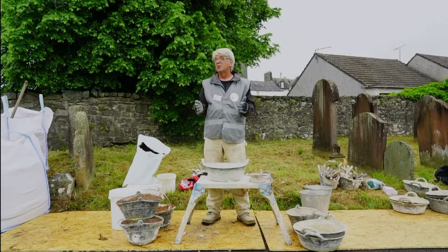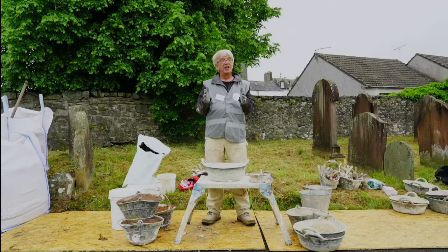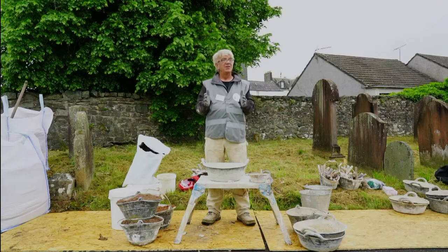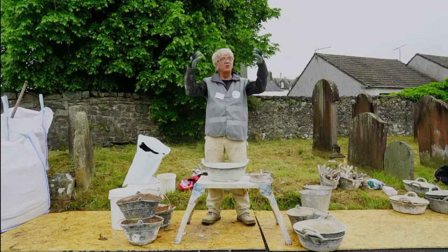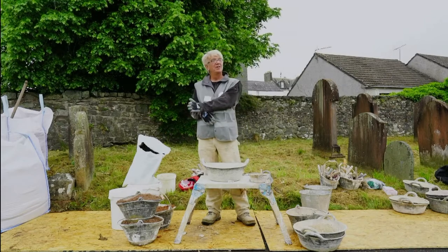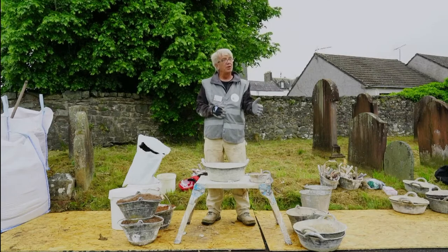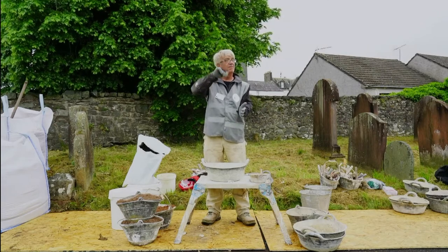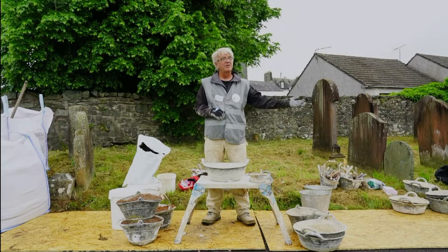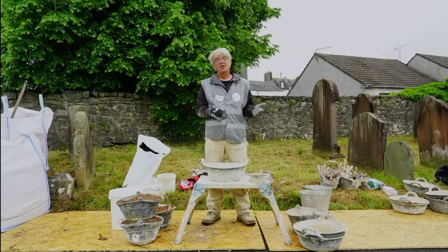Because they don't have cavity walls in America. They're building walls with cement sand mortars, and they're leaking like sieves. So the US Bureau of Standards, what's going on? So they then came up with cement lime mortars as a mortar that gave you pretty good workability because of the lime in it, but early rapid set because of the cement in it, early rapid initial set.